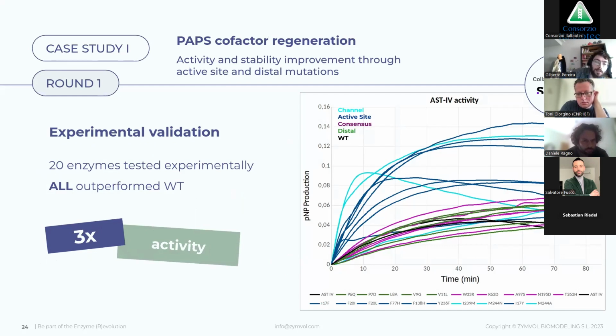Here, PNP production is being measured because you're removing the sulfate group from PNPS, so you're measuring the production of PNP. Indeed, active site and channel mutations were the ones that actually led to the highest increase in activity.